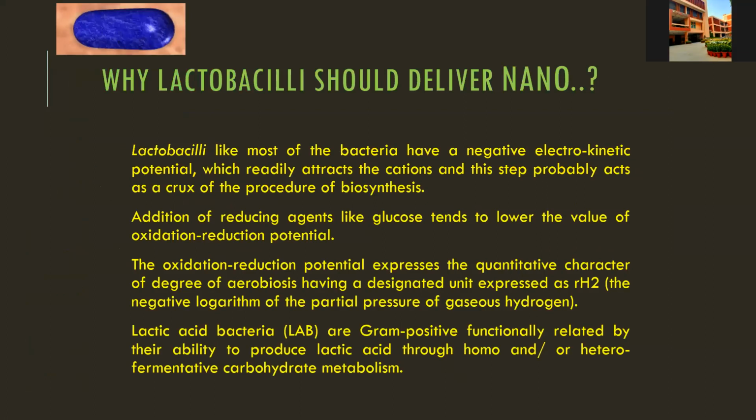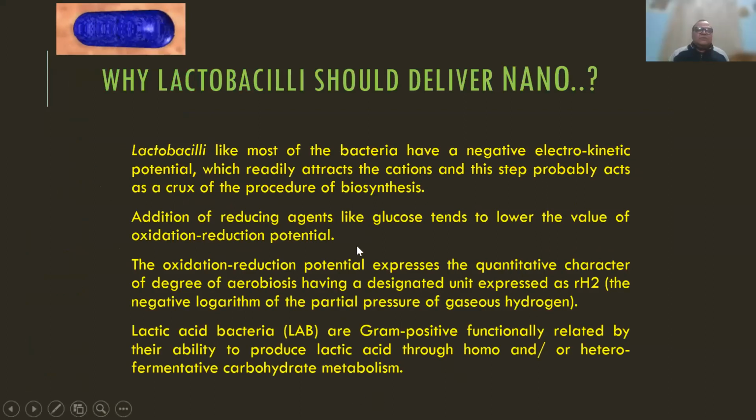So here I'm picking up lactobacilli. Like most bacteria, they have a negative electrokinetic potential. This fact was deciphered in the 40s. It's nothing new I'm suggesting. Addition of reducing sugars like glucose tends to lower the value of oxidation reduction potential, and this oxidation reduction potential is designated as rH2, the negative logarithm of the partial pressure of gaseous hydrogen.